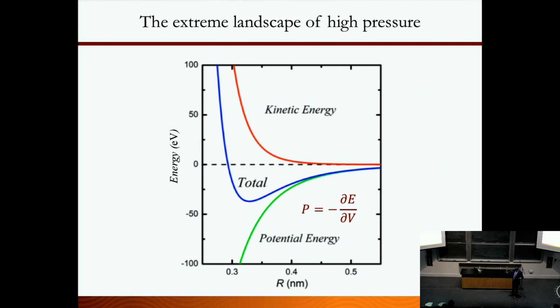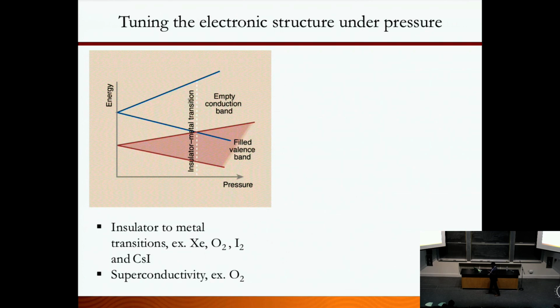You're really changing the energy and trying to manipulate the twin, the bond, and everything, so that you can make a material that has unusual properties. Another interesting property that can happen under pressure, which as a physicist is much more interesting for me, is if you take an insulator, a wide bandgap insulator, which has a gap. Let's say a very transparent material, and then when you subject that to pressure, at some point the empty band and the valence band are going to cross each other, and then you're going to have an insulator to metal transition.